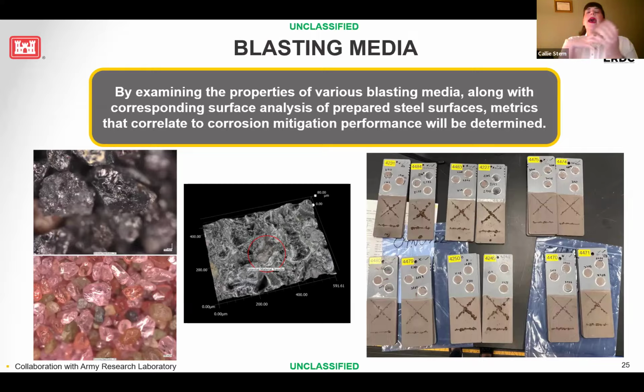And hopefully have some form of corrosion protection. So we're in the process of trying to figure that out. But if you look at the images to the left, you can see some panels. All of these panels were treated by different grit sizes of the garnet material. And what you can see is that there's some that don't really have any rust creep under the scribe, and then some do. So this is kind of giving us an idea of what is the actual size we need to be able to effectively embed material, but also prepare the surface to hopefully have these corrosion mitigation properties.